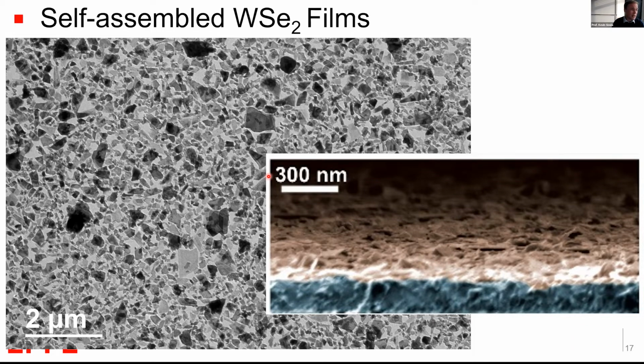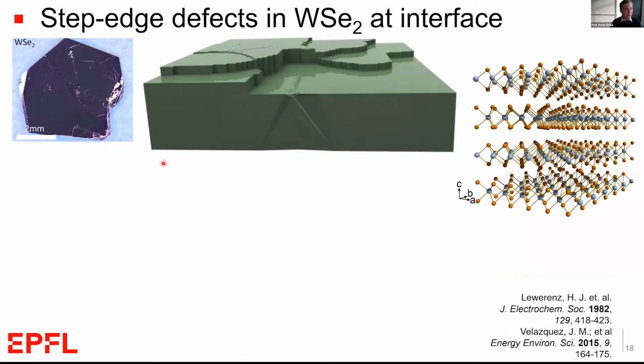Now, another problem here is all of these edge defects. These cause recombination, and initially these films didn't work very well for solar hydrogen production, but we found a way recently to overcome that. Let me just explain the reason why these edge defects are so problematic in these materials. The reason is based on the anisotropic charge transport in these nanoflakes.